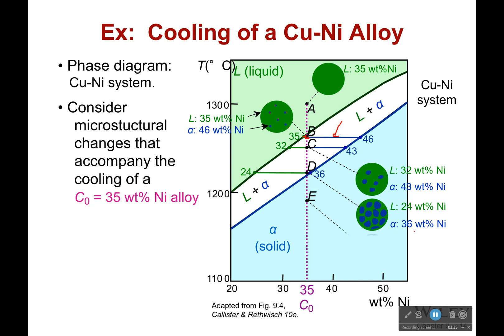Until finally I cross over and now I'm a hundred percent solid. So you see these grains, they began to form, they grew larger, and then eventually they coalesce into one whole solid which is 35 weight percent nickel again. So we start at 35 weight percent nickel, we end at 35 weight percent nickel. And sometimes in between we have different fractions, but as long as we are cooling slow enough, it will all have the same composition at the end.